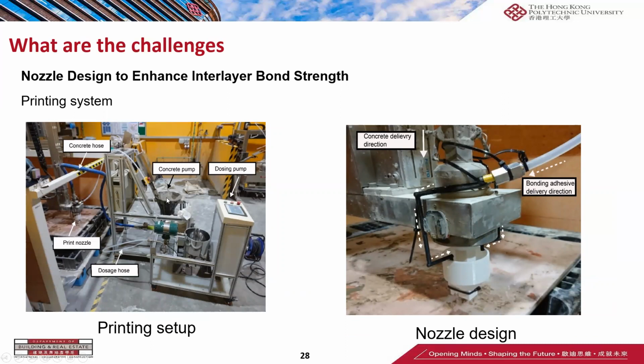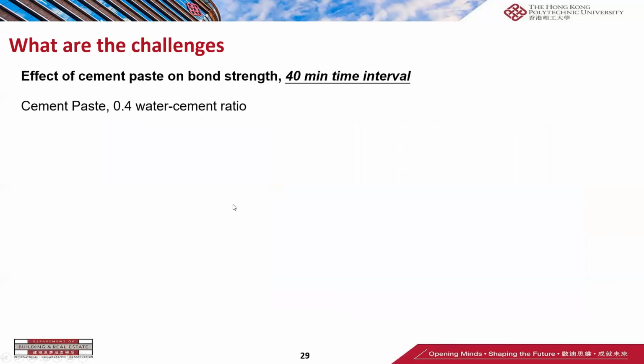We have two delivery systems. One is for the concrete, we call it a concrete pump. We also have another pumping system, which is for the bonding agent. In the experiment, we are using cement paste with a 0.4 water to cement ratio as the bonding agent to enhance the bond performance. And the time interval between the layers is 40 minutes.